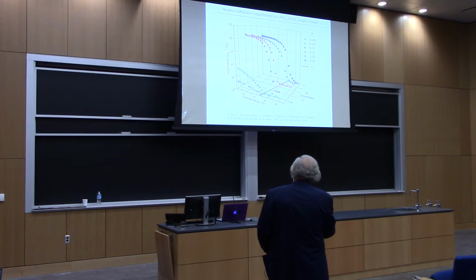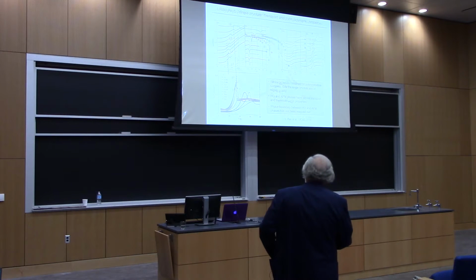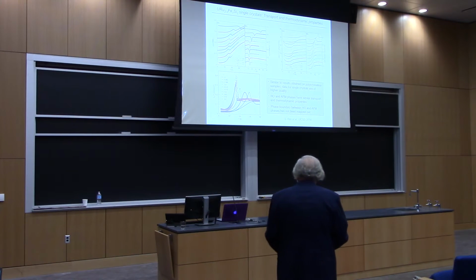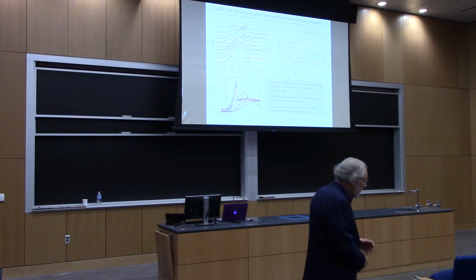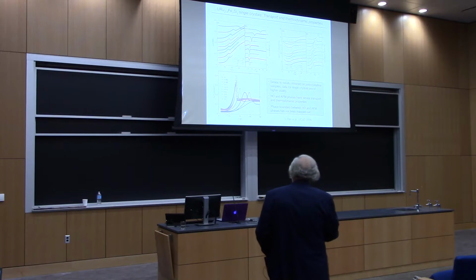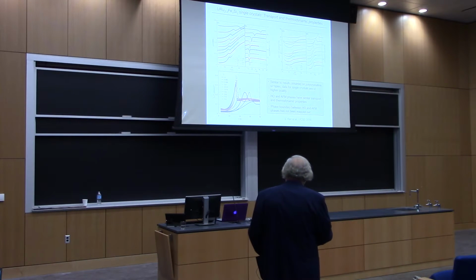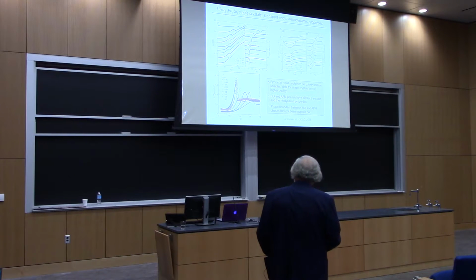This is magnetic moment versus temperature at various values of x. x = 0 is right here, and x increases this way. You see that the moment increases, then you hit an ordered phase, and then you reach a maximum value, after which it slowly decreases. Based upon the magnetization, this shows the transition from the hidden order to the large moment antiferromagnetic phase. This is work on single crystals, so we've done everything over again on single crystals that we did on polycrystals. These are similar to the results obtained on polycrystals, but the single crystal data are much higher quality.